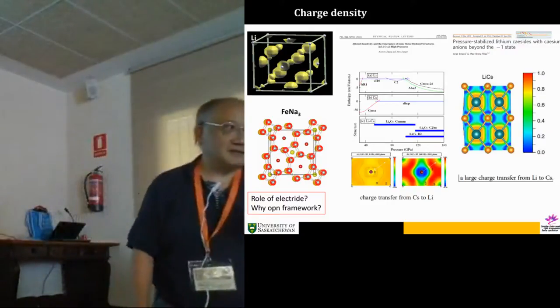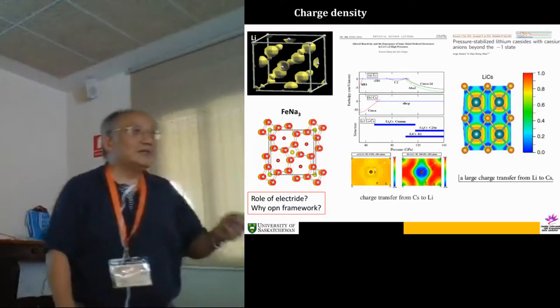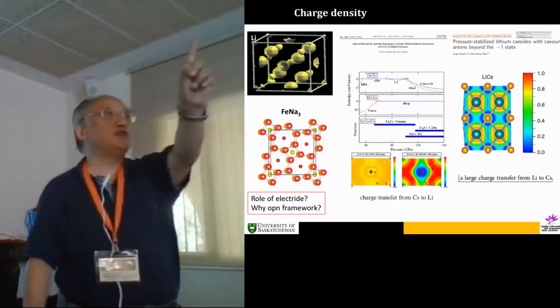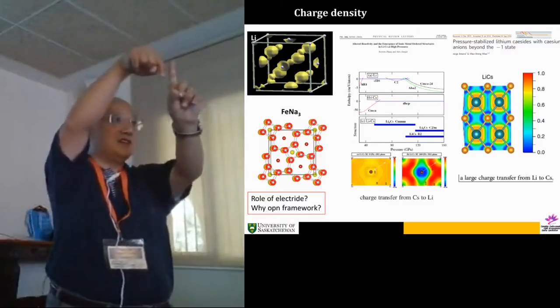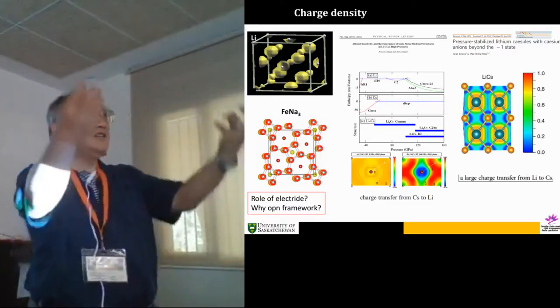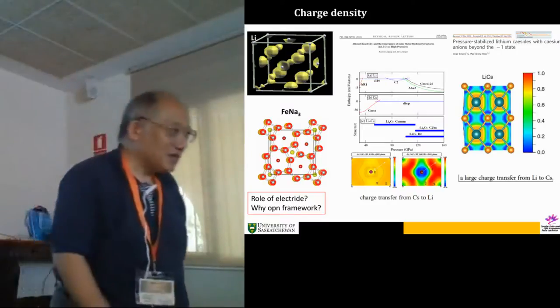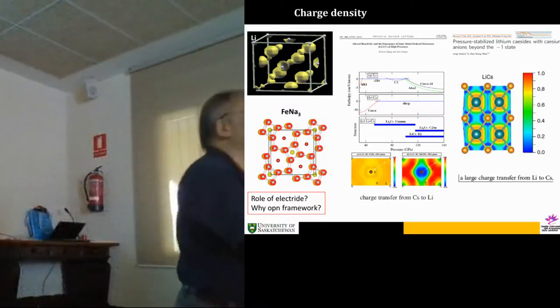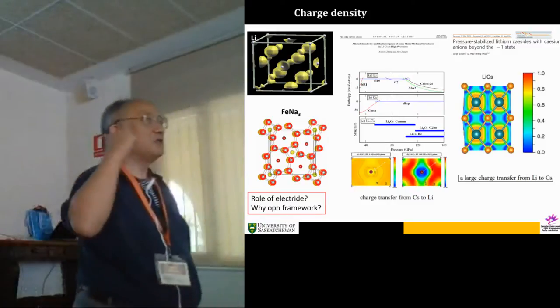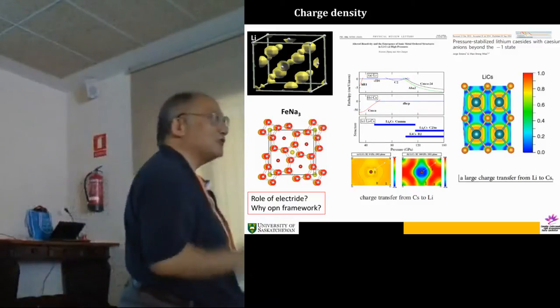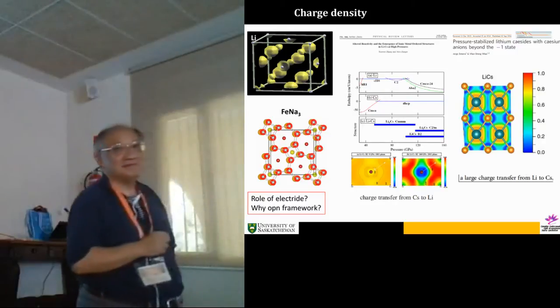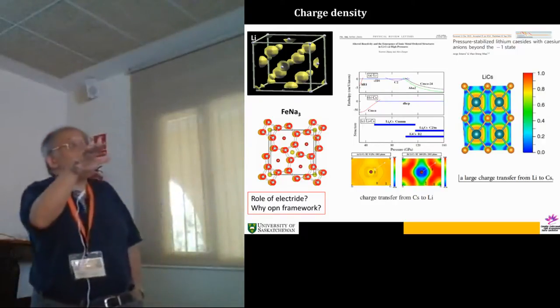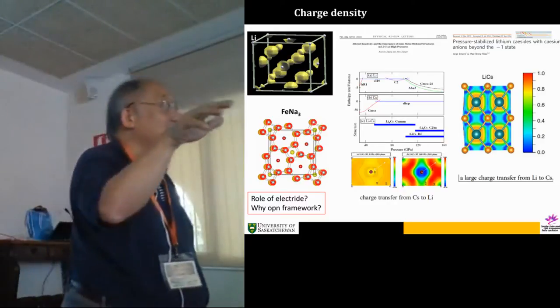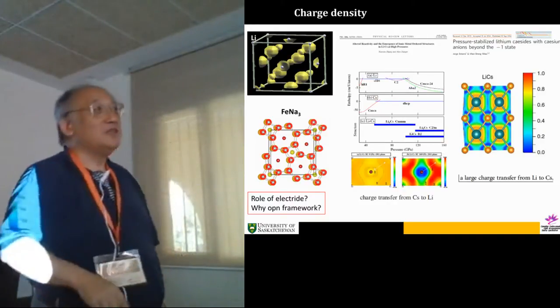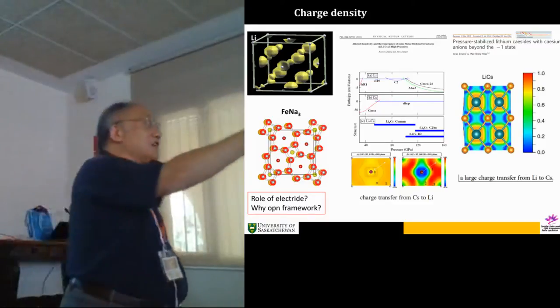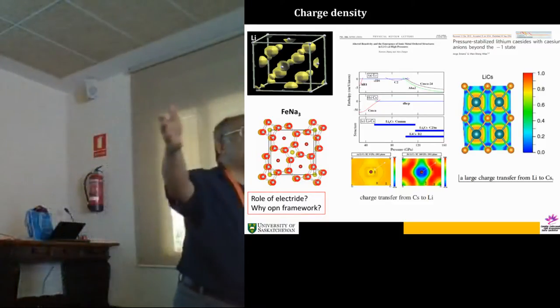Lithium has three electrons, 1s2, 2s1. So the valence s electron is removed from the nucleus and from the electride and pairs up in the blob of electron here, and you end up with two lithium plus atoms. Now, if you get a good diffraction pattern at 450 GPa, how are you going to solve it? When you do the refinement, what do you do? You click lithium, click lithium. So what's the scattering factor table? How is it calculated? Does anybody know how the scattering factor table is calculated?